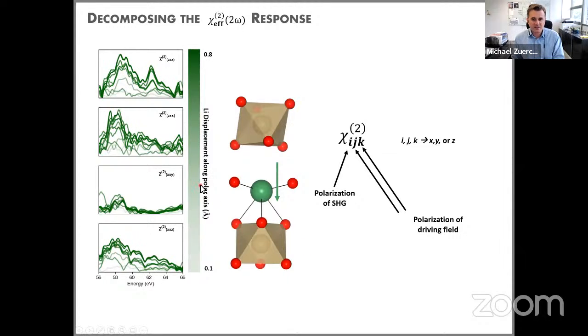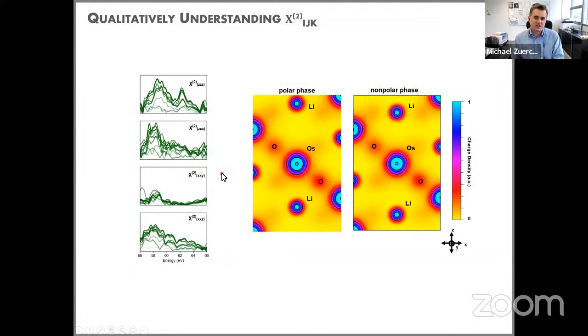I just want to show that now for a few selected cases. What you see here are the numerical simulations for Chi2 for these 4 independent Chi2 tensor elements for different lithium displacements. Lithium displacement is mapped here in the color map from light green to dark green, from 0.1 angstrom to 0.8 angstroms. And you can now at least try to get some qualitative insight into what this really means. I wanted to show just 2 examples.